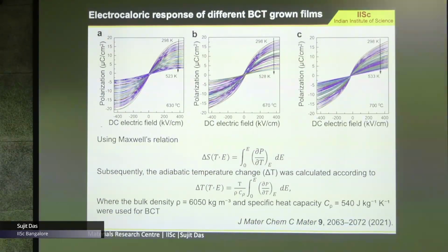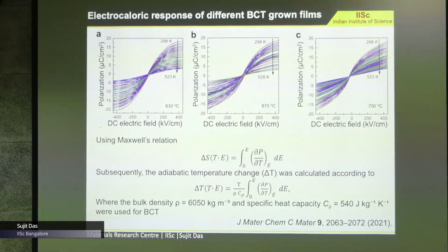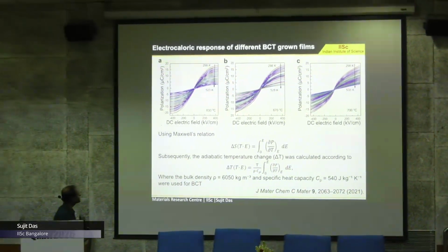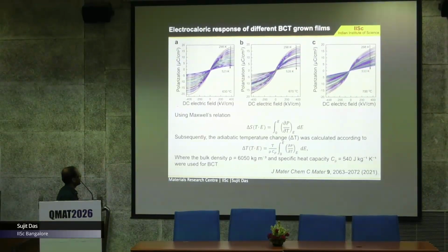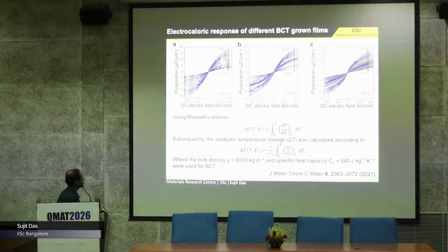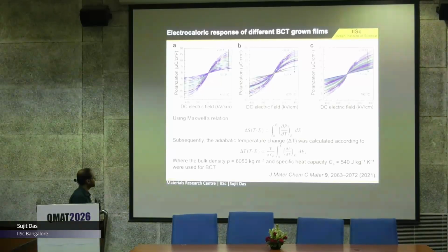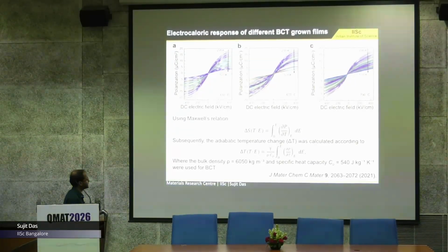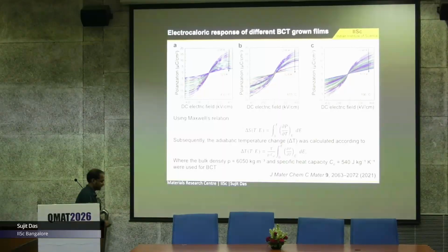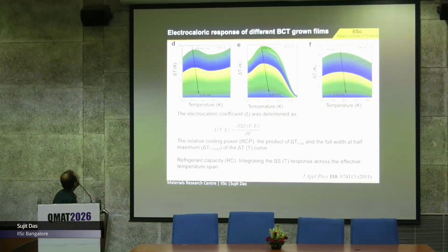And we measure that. For that, first we need to measure the P-E loop at different temperatures, and using the Maxwell relations we calculate the entropy change, which involves dP/dT dE, and from that we can calculate the adiabatic temperature change using these equations. Rho is the bulk density, and C is the specific heat capacity for this particular material. After that, we found that the temperature change is highest for the film grown at 700 degrees C.